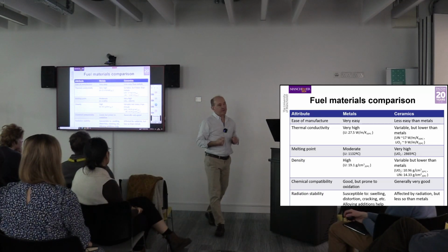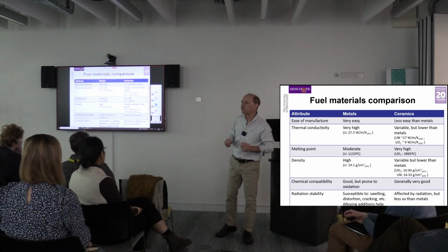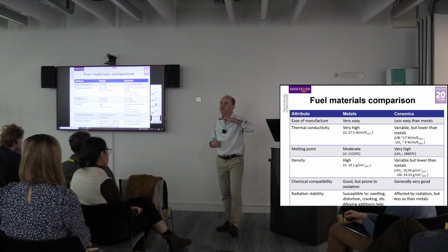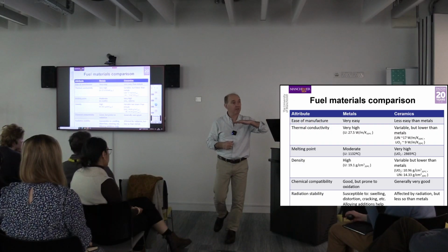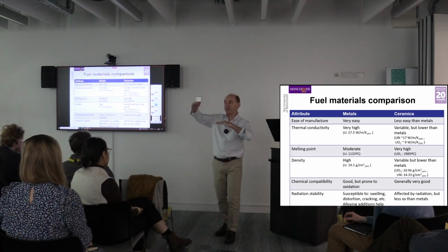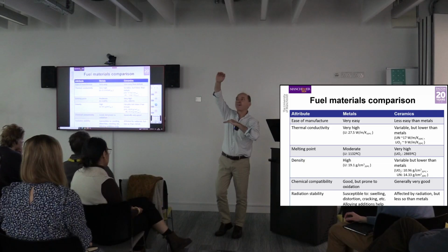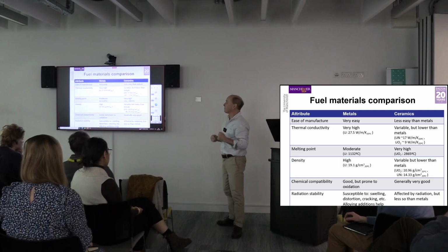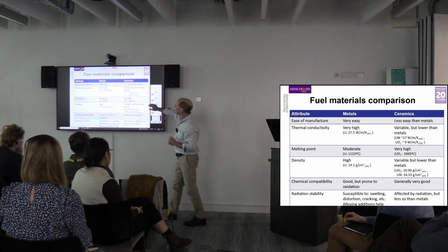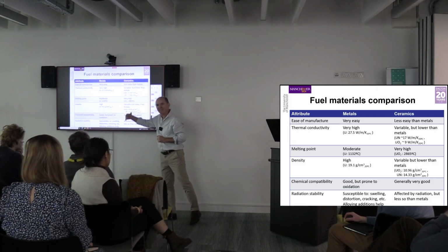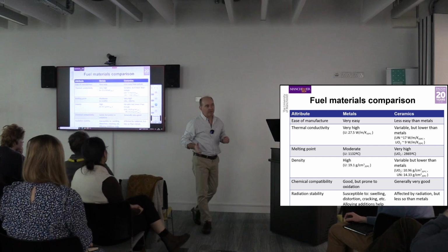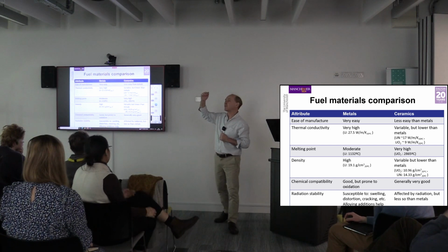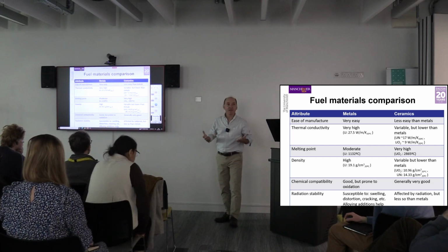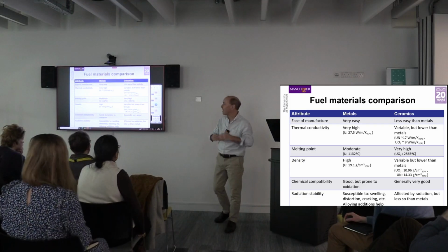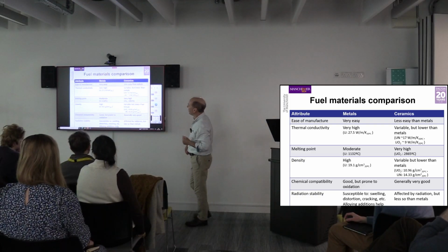So even though UO2 is a really bad conductor of heat, and therefore, under normal operating conditions, operates at quite high temperatures, the safety margin, when we look at where things go wrong, is really high. So surprisingly, somewhat, UO2 is a pretty good choice. Yeah, it's not good at conducting heat, absolutely not, but the melting point is so high that we can accommodate that. We can get away with that because the safety margin is very big.